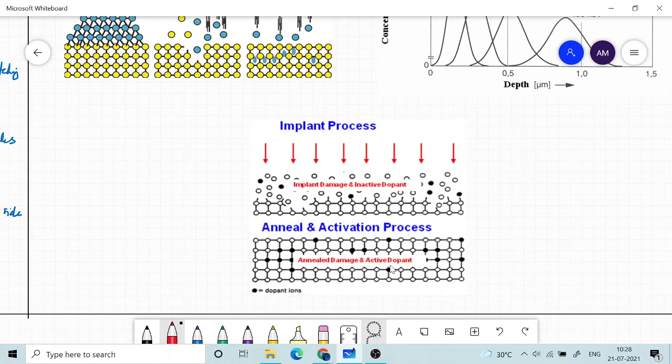In the meantime, the atoms will take their positions according to the crystalline structure. So it is like a repairing work. Ion implantation spoils the crystallinity, and in order to restore it, we do the annealing, and automatically, because energy gets minimized when atoms sit in the equilibrium position, which is defined by the crystalline structure.